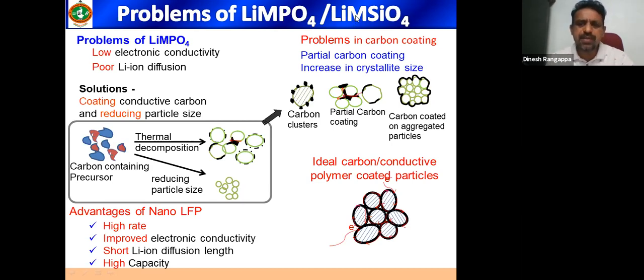And also lithium metal silicate, here two lithium Li2 metal silicate, iron silicate or manganese silicate. So basically these type of materials are having a poor electronic and ionic conductivity. So in the initial time, people developed a strategy, carbon coating strategy through thermal decomposition and coating carbon on the particle surface, and also reducing particle size to nanometer size range, so that we can have better lithium ion diffusion.